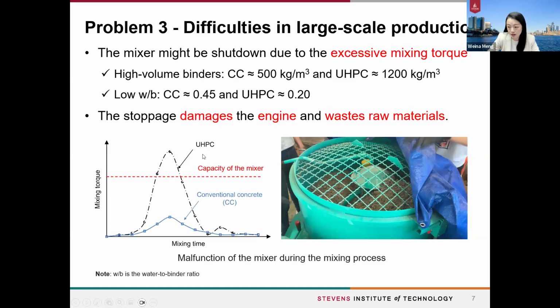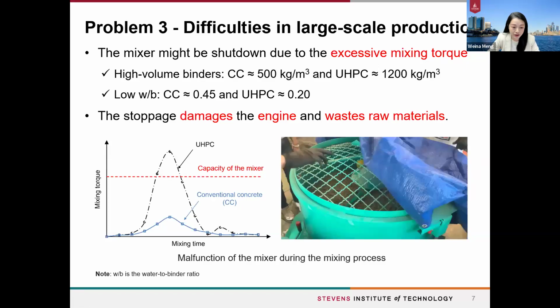But for UHPC, if you mix the same volumes as the conventional concrete, the peak mixing torque will easily surpass the capacity of the mixer, and that causes the stoppage of the mixer, and that may damage the engine of the mixer and waste all the raw materials. So those are the three critical challenges we identified.